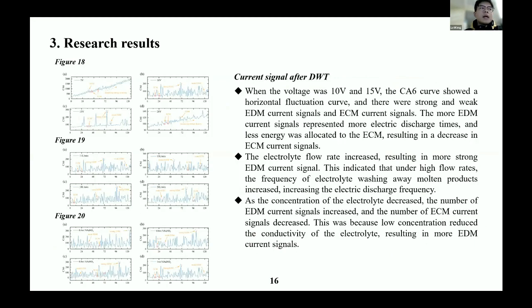The signal processed by DWT shows that the voltages at 10V and 15V are relatively stable discharge voltage stages with strong EDM, weak EDM, and ECM signals present. After the electrolyte flow rate increases, more EDM signals appear, indicating that the effect of EDM is enhanced when the electrolyte washes away some of the molten products. As the concentration decreases, the decrease in conductivity leads to an enhanced effect of EDM and a weak effect of ECM, resulting in more EDM signals at low concentrations.